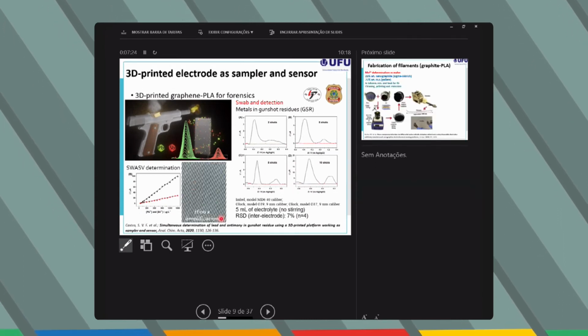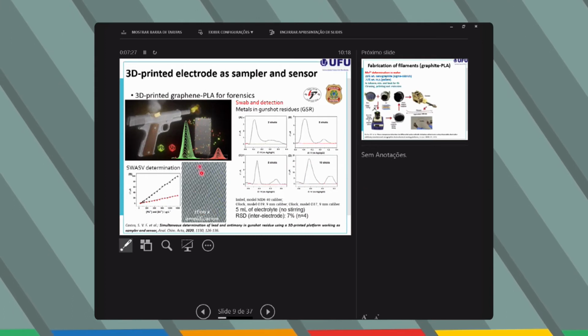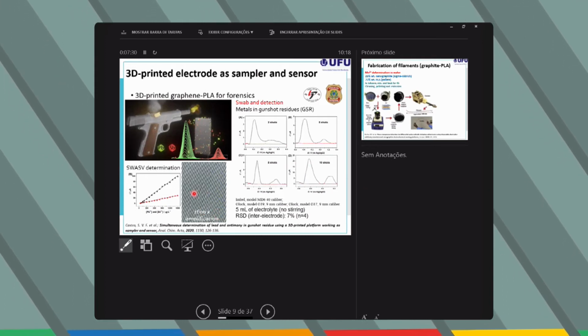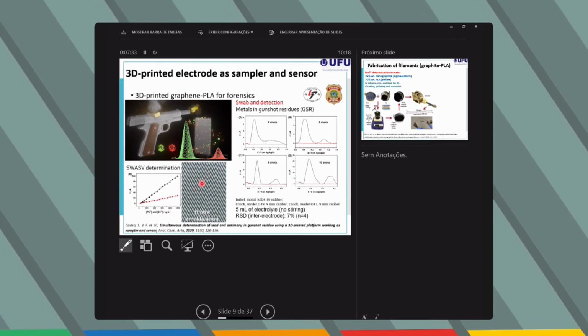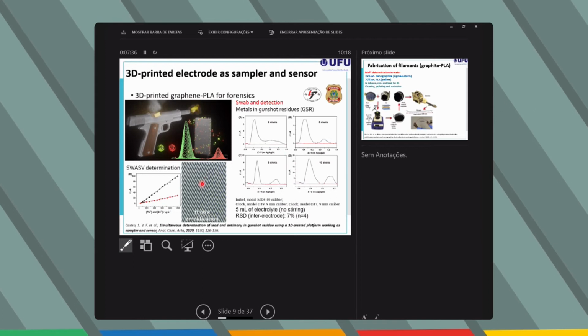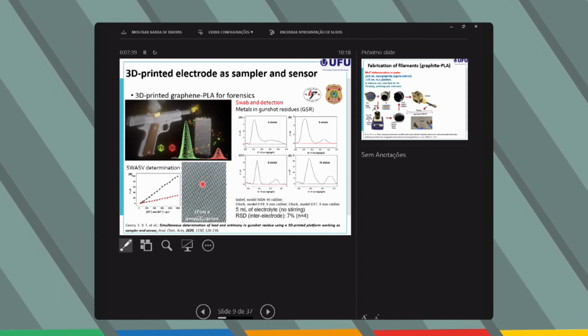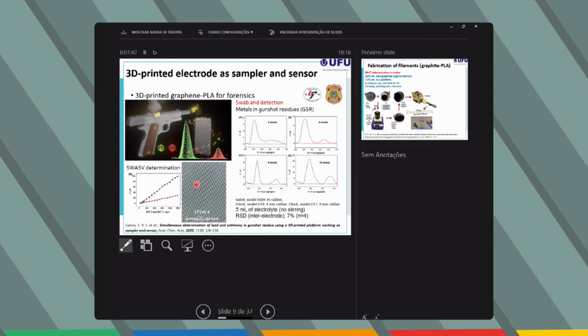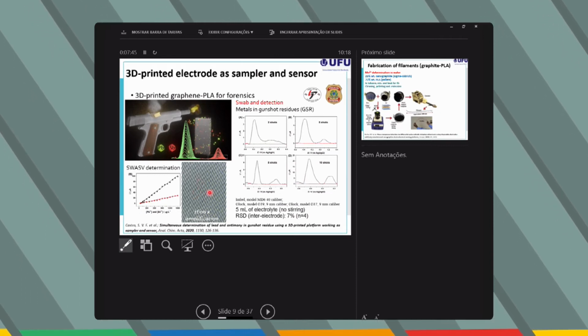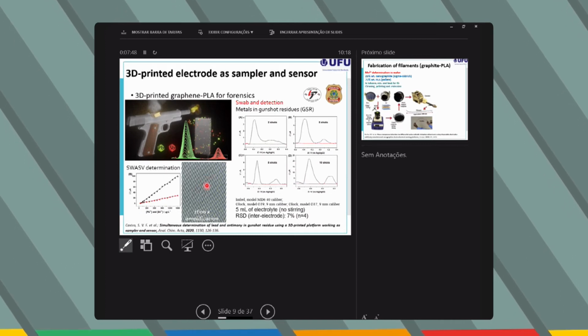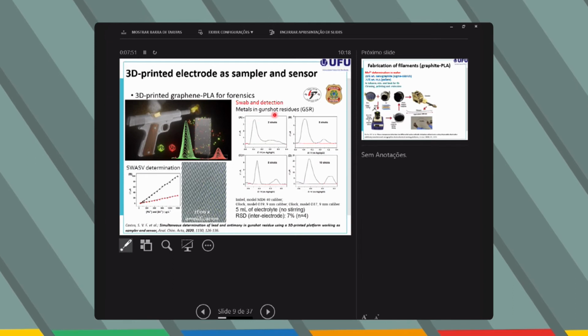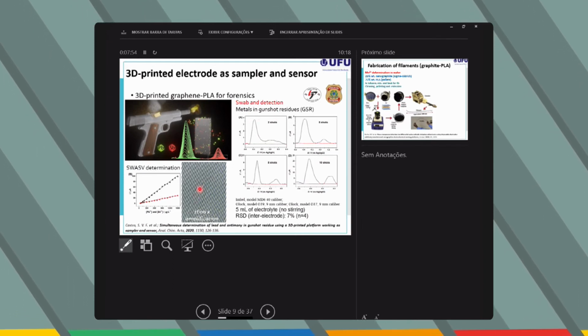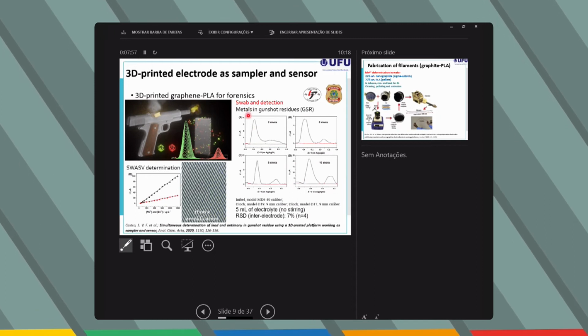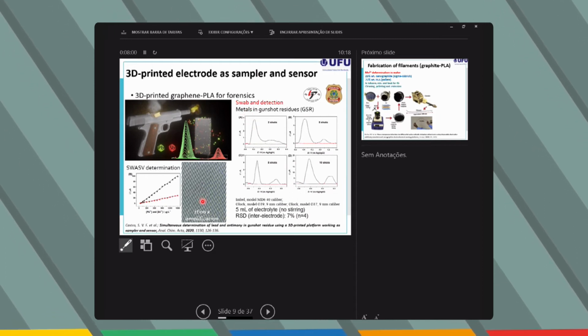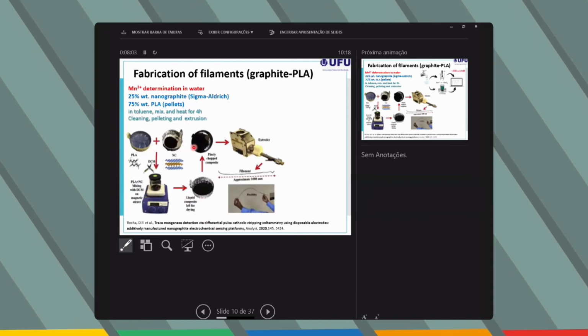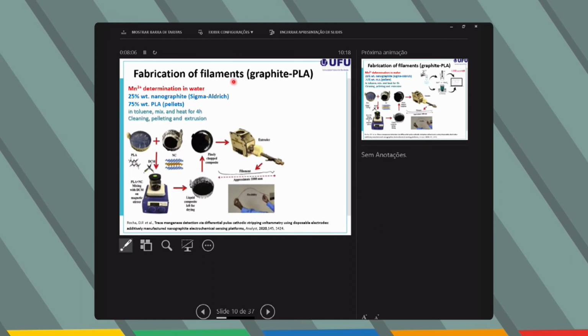This is an amplified image of the same 3D printed material. Here you can see some parallel lines that are typical of the layer-by-layer deposition. Every line here indicates the height of deposition, which is around 100 micrometers. Beyond the possibility of using a porous material that is very good for the collection of these gunshot residues, it's also possible to have a very good electron transfer from the metallic species to the electrode surface and then for the detection.